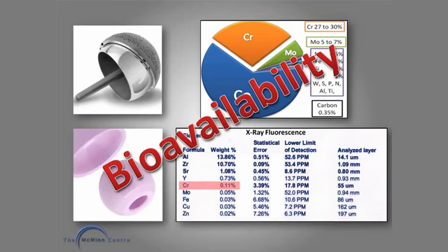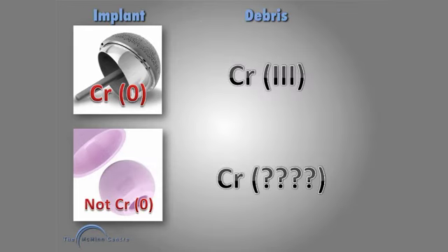We know for certain that the chromium in a metal-metal joint is chromium 0, and we know for certain, because it has been measured, that the chromium in the debris from a metal-metal joint is chromium 3. Both of these chromiums are harmless. Now, I'm told by those who should know that the chromium in delta is definitely not chromium 0, and the ceramic chemists have no idea what the chromium from a delta-delta articulation is in the debris. And the concern, of course, is, with this unknown, could it possibly be chromium 6?